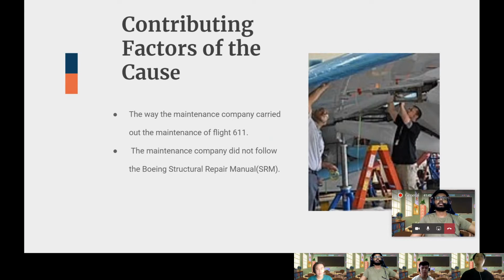The crash would not have occurred if the doubler was installed properly, as the damaged skin was not trimmed properly and the repair doubler did not extend sufficiently beyond the entire damaged area to restore the structural strength. This means that all the scratches would be completely contained by the innermost row of fasteners, and the fasteners themselves would be strong enough to stop the propagation of any new and existing fatigue cracks. However, the installed doubler was too small and therefore failed to effectively cover the damaged area where scratches were found, outside the outermost row of fasteners meant to secure the doubler. The installed doubler, with scratches outside the rivets, provided no protection against the propagation of any concealed cracks in the area between the perimeter and the row of rivets.